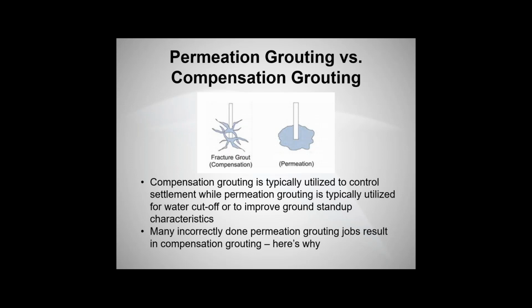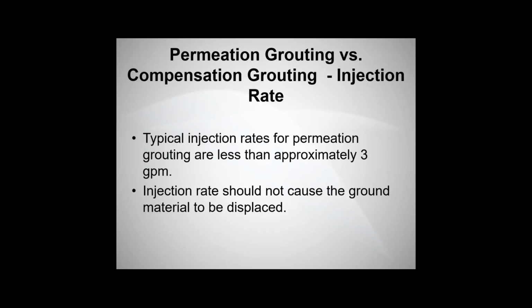But again, the point here is that a lot of the times, if permeation grouting is done incorrectly, it turns out to be compensation grouting, and we'll talk about why. For permeation grouting, your injection rates are typically going to be very low for what most people consider injection rates to be. A lot of the times, you're going to be at 3 gallons per minute or less, kind of as a rule of thumb.